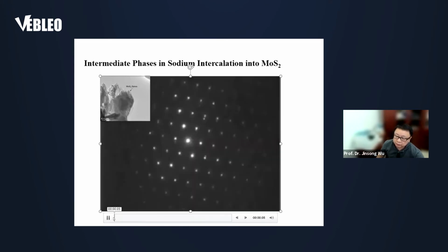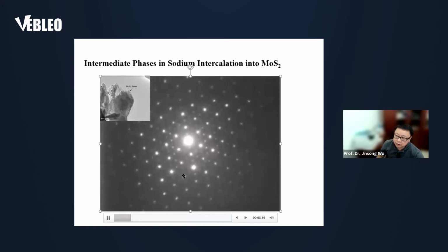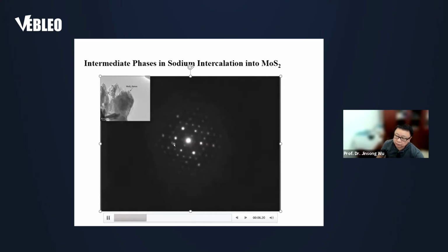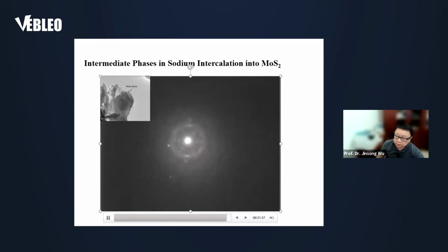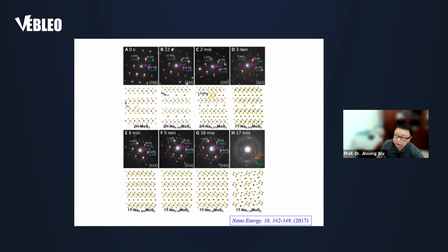So what we can observe is, first of all, we have MoS2, and then gradually we have a lot of superlattice. See here, extra diffraction spots appear. And then gradually we have, again, highly diffuse ring patterns. This is the sodiation process, so instead of using lithium, we use sodium. And if we look carefully at each experimental diffraction pattern, and also use the DFT simulation and the image simulation, what we can find is